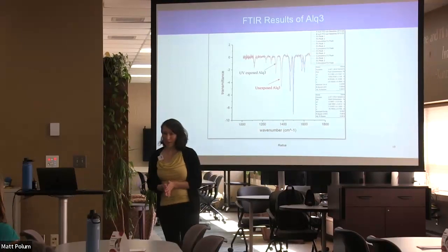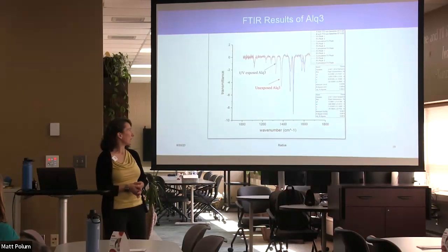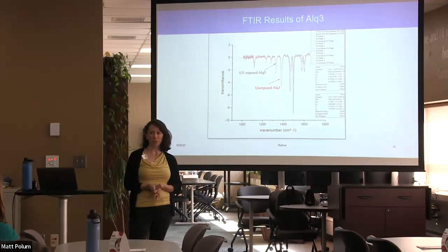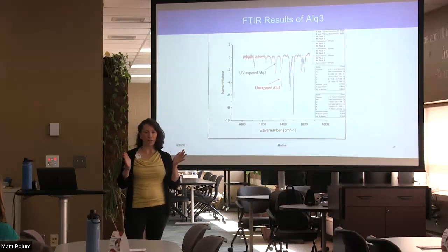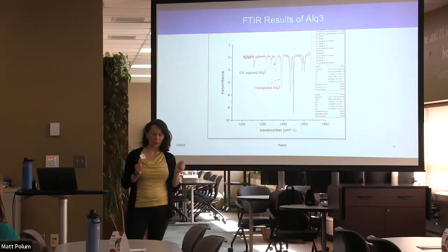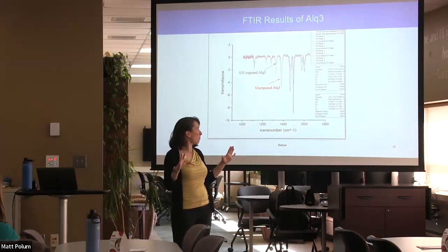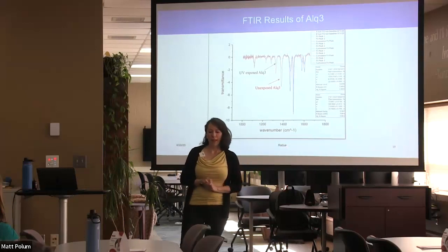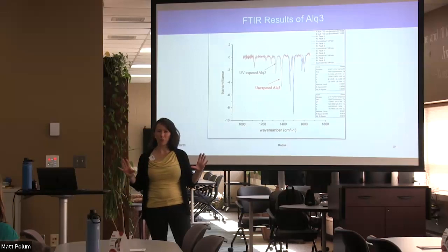So what can we say about this? Well, we're still working on interpreting this. But I will say we haven't seen any of these peaks shift. So that tells me that the frequencies of any of these vibrations are not changing. So that's not going on. And we see an overall decrease in amplitude across most of these bonds here. And that suggests to me that we have bonds breaking just kind of across the board.